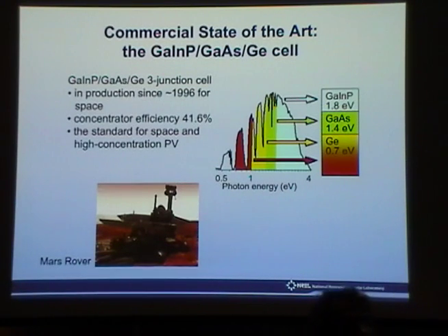So what's the unconcentrated efficiency that the Mars rover is actually using? Well, let's see, under 1 sun concentration terrestrial, the world record is about 34%. And for the space spectrum, it's probably a little higher, but I don't have it quite. So mid-30s. Mars is farther from the sun. But the space spectrum has about 1,360 watts per square meter, so it's a higher energy spectrum. It's tilted toward the UV.